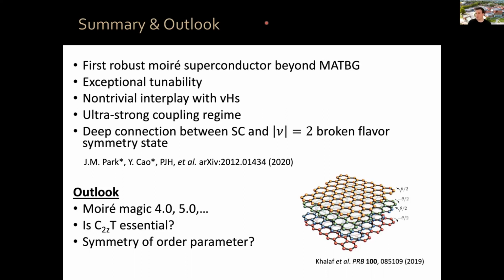Most groups, probably because we've been doing it the longest, it's like 1 in 10 or 1 in 100 type of luck with hitting the twist angle, etc. But larger angles are more stable and are easier to nail down. So it could be that the system is a bit more robust also from that point of view.